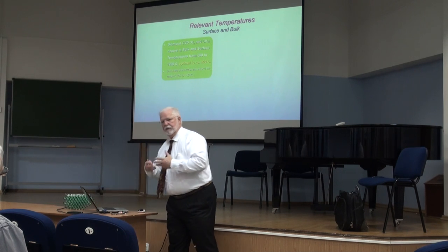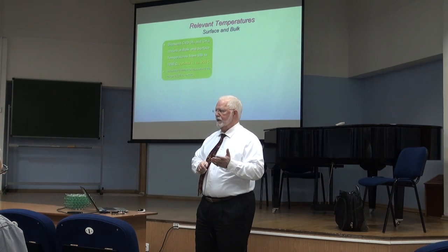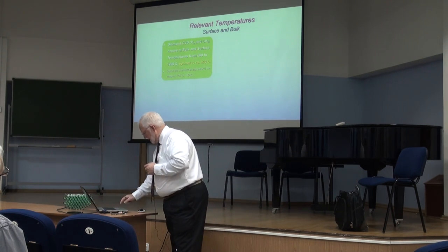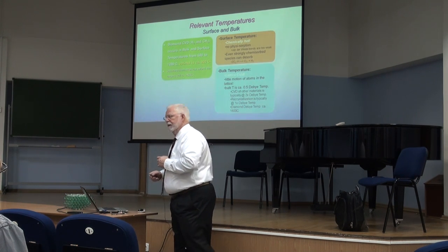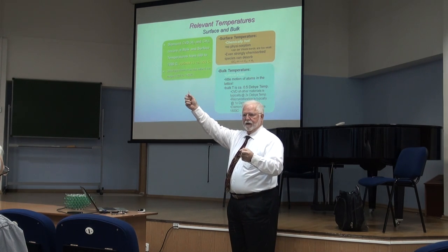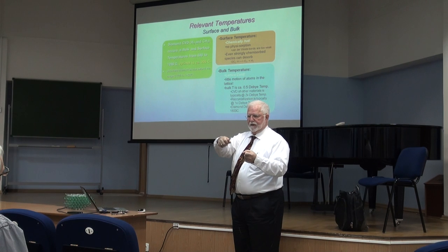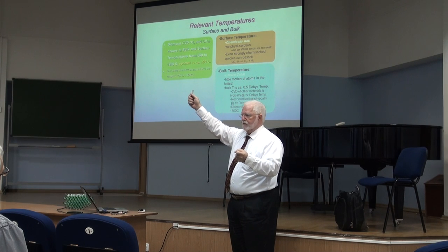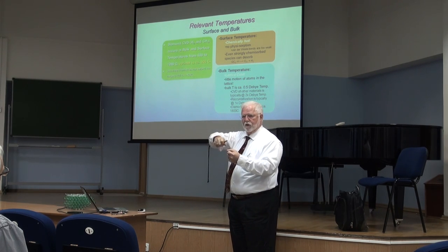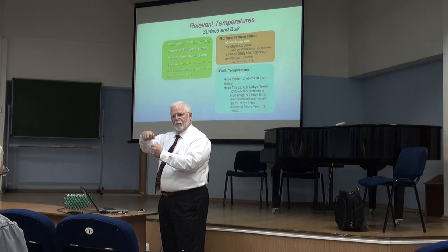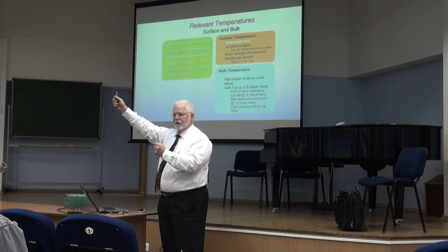Now we're going to grow diamond in the reactor at a temperature typically 850 to 900 degrees C. That's much cooler than in Earth or in high pressure. But from a chemistry point of view, that surface is like a frying pan. It is so hot that if an atom or a molecule comes to bond to that surface, it can't just van der Waals or physisorb because the surface is so hot it goes right back to the gas phase. Even if it comes and it makes a strong chemical bond, a C-C or C-H bond, at that temperature, there is a slow but reversible process where the carbon-carbon or carbon-hydrogen bond can desorb and go back to the gas phase.